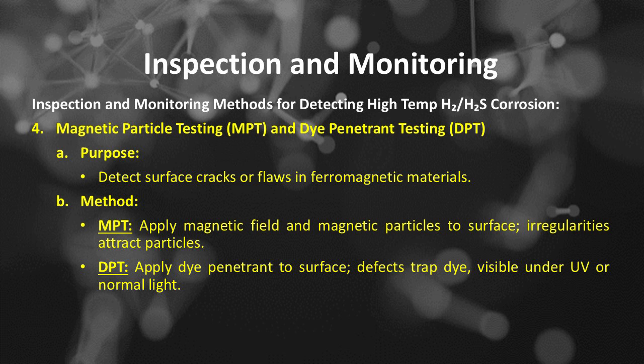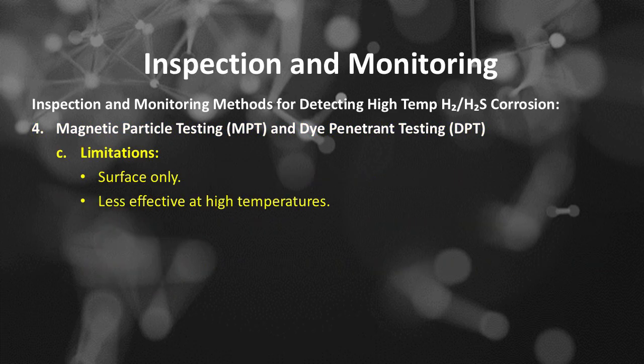Inspection and monitoring methods. Number 4 is magnetic particle testing, or MPT, and dye penetrant testing, or DPT. This is purposed to detect surface cracks or flaws in ferromagnetic materials. The methods of MPT and DPT include: MPT applies a magnetic field and magnetic particles to the surface, and irregularities attract particles. DPT applies dye penetrant to the surface, defects trap dye, visible under UV or normal light. The limitations of MPT and DPT include: surface only, less effective at high temperatures.